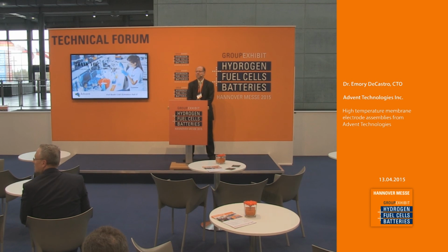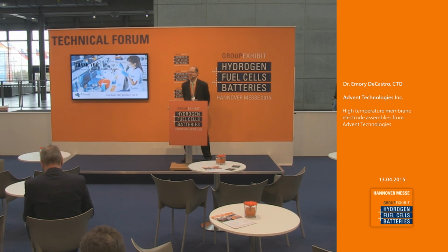I can open the forum now for any questions from the audience. Thank you. How about the influence of CO to the MEA? So today, operating at up to 180 C, we can take 3% CO. We've actually run up to 7%, but there certainly is a polarization loss at that point. At 200 to 220 C, which is more our developmental product, 5 to 7% is achievable. So you mean today is about 180 degrees? Yes. And 3% is easily achievable. OK, thank you. That's percent, not PPM, percent.